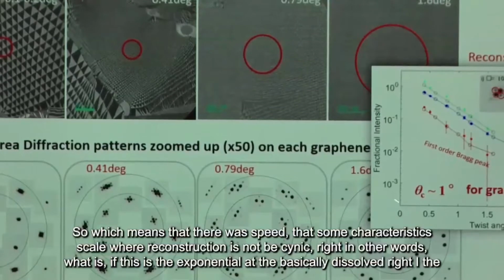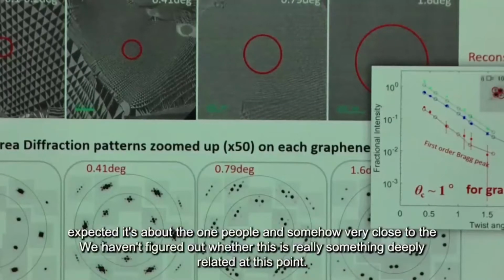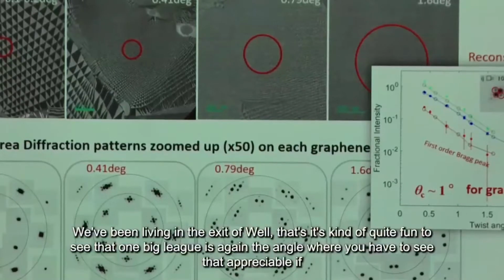It turns out that the characteristic angle where the reconstruction is significant is about 1 degree, right? And that's very close to the magic angle. We haven't figured out whether this is really something deeply related. At this point, we believe it's accidental, but nevertheless it's quite fun to see that the magic angle is again the angle where you start to see appreciable reconstruction happening.